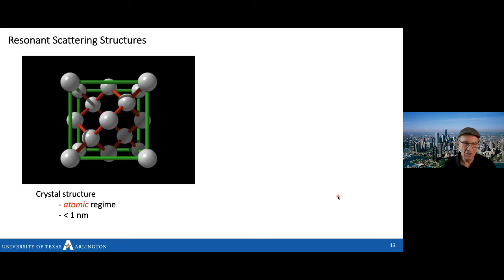So the quantum dot we thought first about was what happens when you make a quantum dot and it's in a background field with nothing. What if you could go the other way and introduce a resonance scattering structure? Now, you're generally, even if you don't know it, familiar with resonance scattering structures because crystals are all resonance scattering structures. They scatter the carriers, and they do this on a scale that's less than a nanometer. So it's very much in the atomic regime.